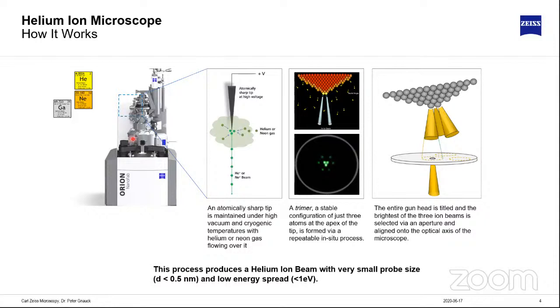And to add some more capabilities to the instrument, so I told you already we can use helium and neon with this gas field ionization source. And we can also add a standard gallium FIB to the instrument where we can do cross-sections and whatever. So then we have a tool which is very similar to a cross-beam, dual-beam instrument where we can use the gallium beam for creating cross-sections, and we can use helium and neon for high-resolution imaging.